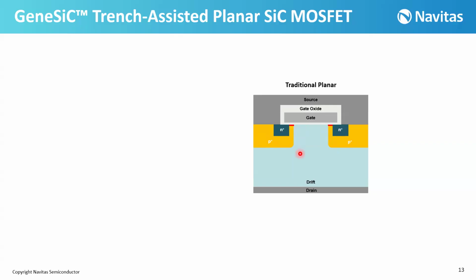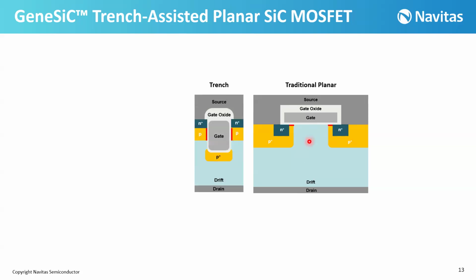Another way, as I mentioned, is reducing the cell pitch. And the third one is that normally in silicon carbide, the electron mobility is not symmetrical, where we have a higher electron mobility in the C axis, which is the vertical part, compared to the XY plane as we have here at the surface of the silicon carbide. And this is the reason that we went to trench devices like this.